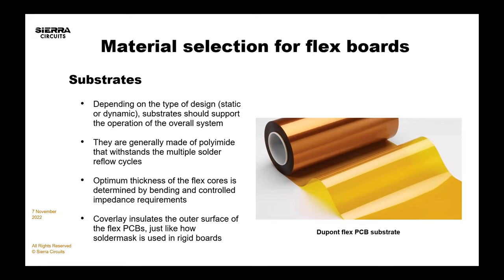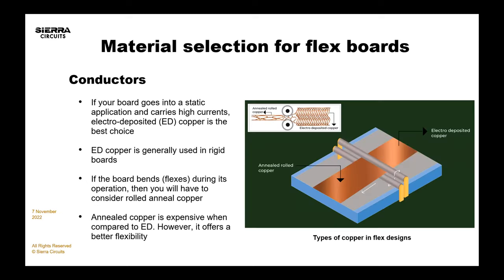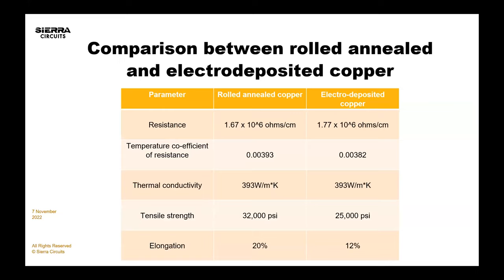We have been doing projects with some flex material manufacturers to help them with their electrical performance. One key difference beyond electrical performance: flex materials use rolled and annealed copper, while rigid boards use ED or electro-deposited copper. Rolled and annealed copper has better properties — its elongation and tensile strength are superior — and that's what makes it suitable for flex applications.